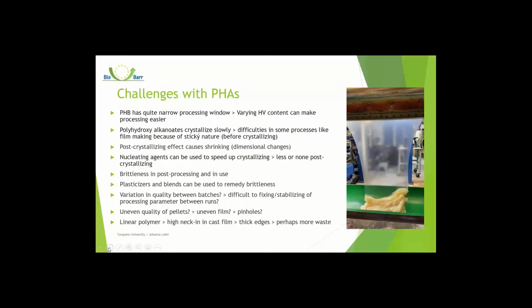Of course, with PHAs, as with some of the other biopolymers, there can be some challenges which we also try to solve in this project. So PHA, for example, has quite a narrow processing window if we talk about extrusion, and by varying this valerate content we can affect the processing in extrusion. Also, the crystallization behavior is something that sometimes causes challenges in extrusion casting processes or coating processes.